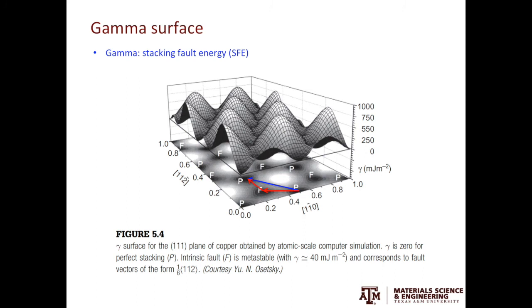Those hills and peaks, they represent a very high energy barrier. Remember we mentioned for FCC crystals, the 111 planes have ABCABC stacking. If we start with plane A, and move the next plane directly on top to occupy the A position, and this is the energy we need to overcome. Apparently, it is not energetically favorable.